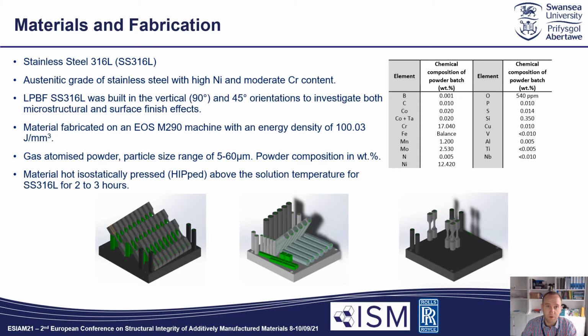For the purposes of this work, we looked at LPBF 316L manufactured in two alternative build directions. So firstly, the vertical orientation, or 90 degrees, and also the 45-degree orientation, to try and understand how build orientation also affects the microstructure and surface finish in different orientations. So a set of LCF specimens were built in the two different build orientations on an EOS M290 machine using gas atomized powder with a particle size distribution ranging from 5 to 60 microns, with a full composition given in the table to the right of the screen.